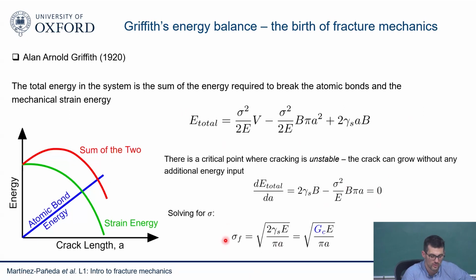And so if you take this, equate to 0, and solve for the stress, this is the applied stress. What you get is that the failure of that plate, which Griffith thought was just reaching a critical stress near the defect, actually, the stress at which it will fail will not be tiny, because it will require some energy. So it will be this expression here: the square root of 2 times the surface energy multiplied by Young's modulus divided by pi times crack length. And you can group this 2 times surface energy into a value that we call critical energy release rate, also material toughness, or fracture energy. So that's the idea.